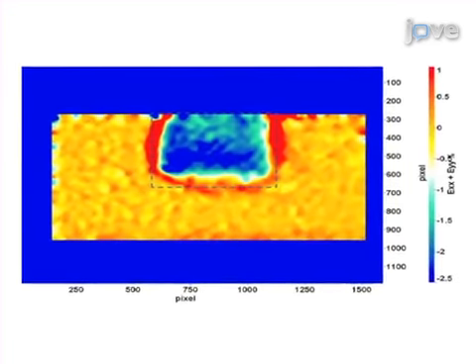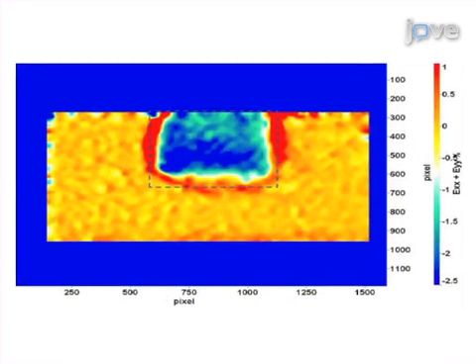Ultimately, results can be obtained that show the areas of strain concentrations where debonding of the resin composite from the tooth surface could occur. The main advantage of this technique over existing methods like strain gauges is that DIC can provide visual images of the strain distribution over the entire observation surface. This method can help answer key questions in the development of resin composites for dental restorations, such as the level of shrinkage stress induced by the polymerization process. Demonstrating the procedure will be Ian Huxford, a junior scientist from my laboratory.